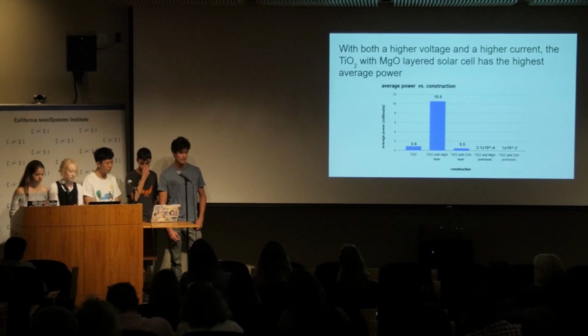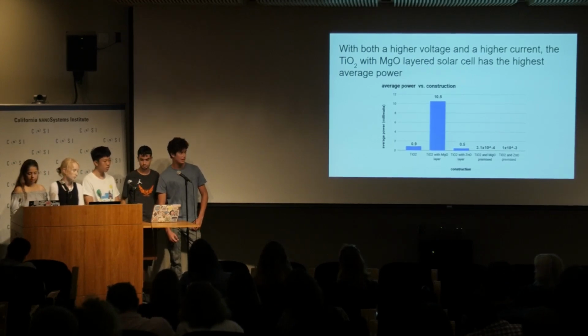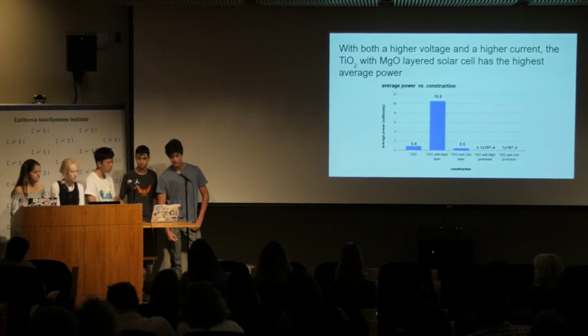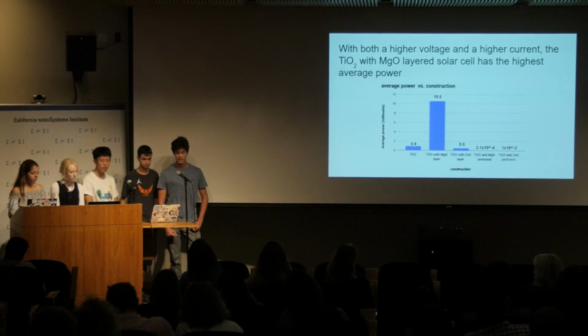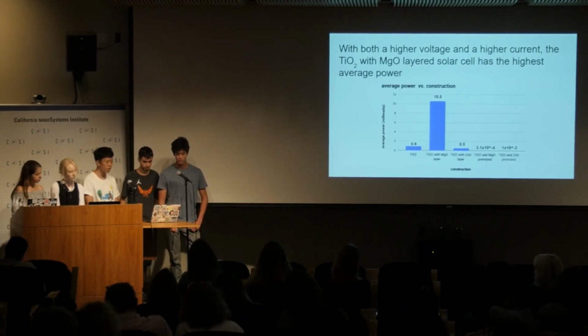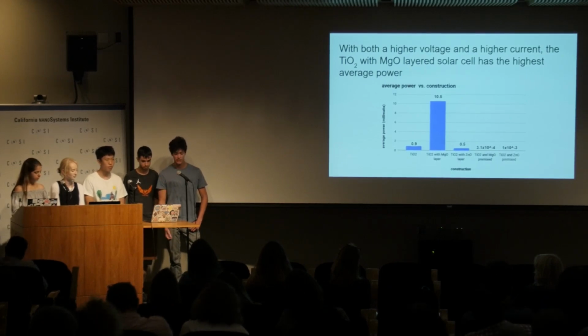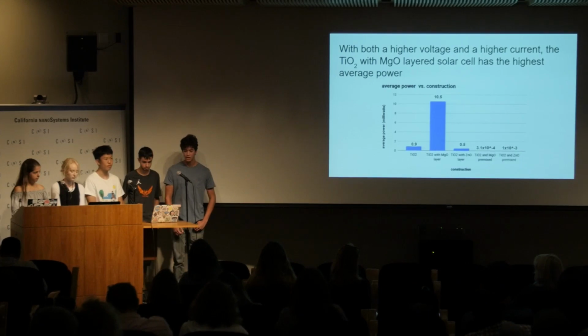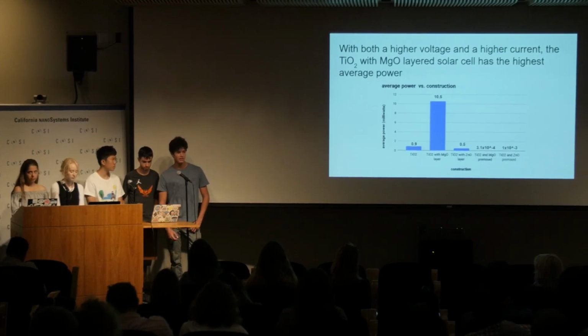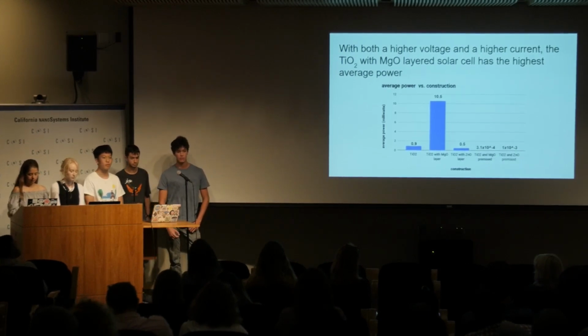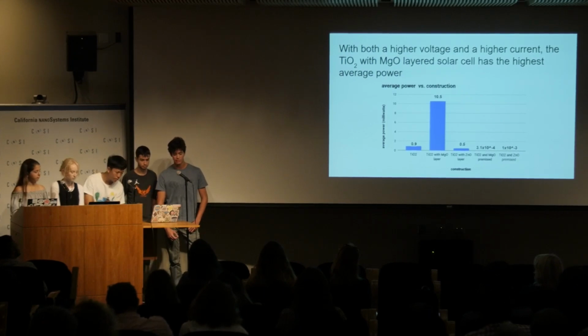So then using the voltage and the current, we calculated power. And as you can see, the TiO2 with the MgO is much higher, and the zinc layer is slightly lower. And so we believe that the reason why the zinc layer had a lower output was because zinc ions would form on the zinc layer, and this would hurt the electron injection, which is basically the emission of electrons from one solid into another, and this would decrease the overall efficiency of the solar cell.